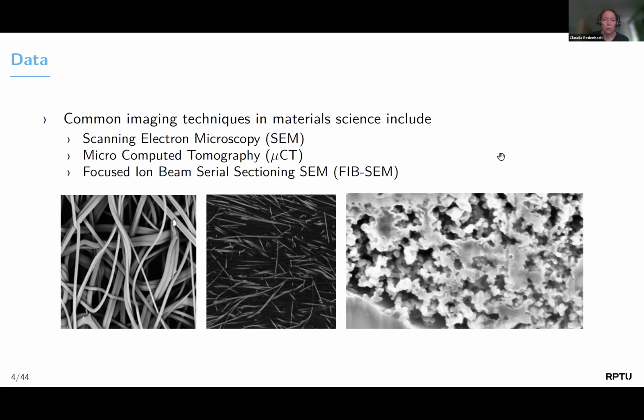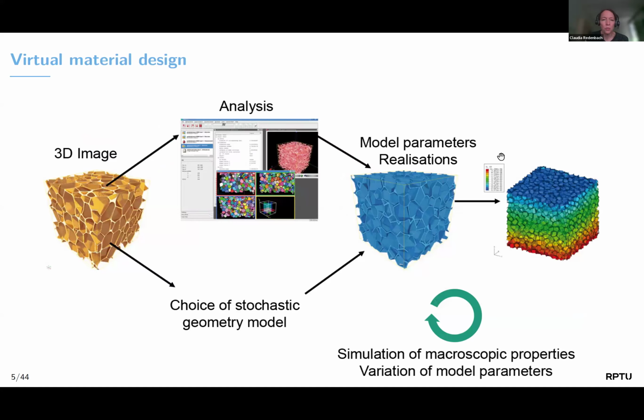Now, given such images, we want to characterize the microstructures, and we will see several tasks of how to do that. Why are we interested in that? We see here the pipeline of what we call virtual material design. On the left, you have a 3D image of a real sample, here a closed cell foam that has been imaged by CT and gives us an idea of how a material that is currently in use may look like. We could analyze the sample, decide on a certain stochastic geometry model, fit everything together, and find model parameters. We would then be able to generate virtual realizations. So now this blue sample here is no longer real, but has been computer simulated, and it tries to match the cell system that we see in the yellow example as closely as possible.